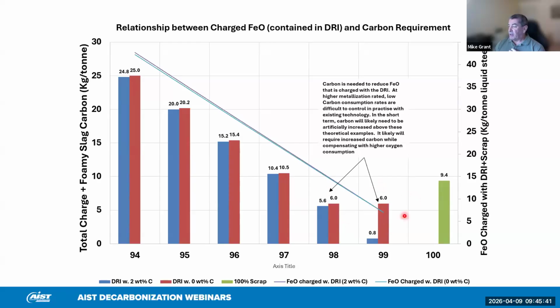One problem with such low carbon injection rates is it's pretty hard to control. Practically, it's pretty hard to control the injection rate of carbon at this low consumption value. And given the fact that with a conventional carbon injection system, you're losing 50%, it's really hard to know what you're putting into the process anyway. But this is going to be a topic that needs to be dealt with as we move towards more hydrogen-based DRI.